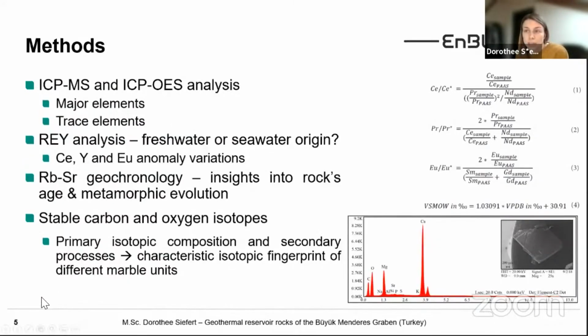And for the geochemical analysis, the surface samples were crushed and prepared for ICP-MS and OES. So with this method, we analyzed the major, trace and rare earth elements. So we used the equations on the right to detect potential rare earth anomalies. And then we did carbon and oxygen stable isotopic composition of the marble carbonate minerals. And this was also determined by mass spectrometry. And the carbon isotopic composition is given in the delta notation, two different standards, oxygen as well.